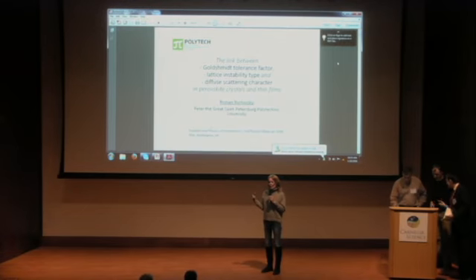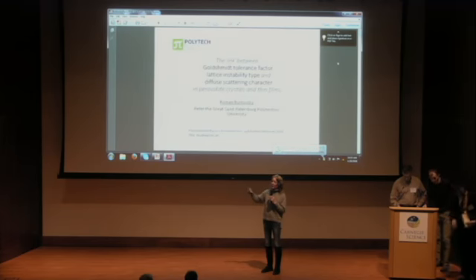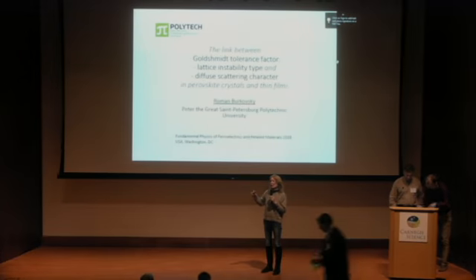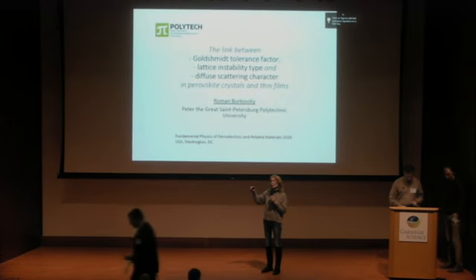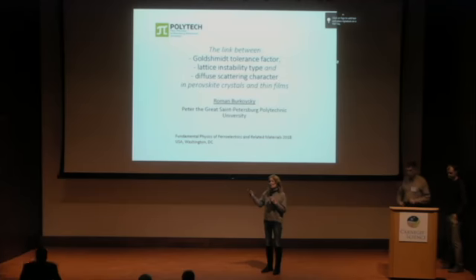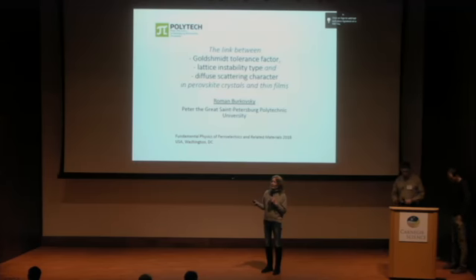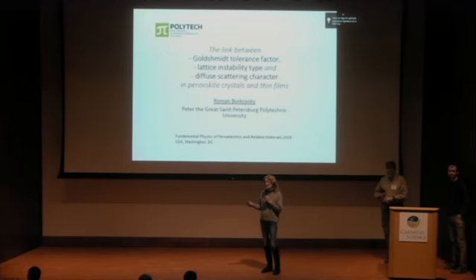Oh, this does not affect the dependence of the two modes on each other. What you see, however, is that the optic mode goes soft indeed, but it does not play a role for the temperature dependencies of the two modes, so they remain the same. But strontium titanate, the oxygen isotope replaced strontium titanate, is also not a ferroelectric in the sense that it is truly ferroelectric, but it's something like also a very inhomogeneous state.